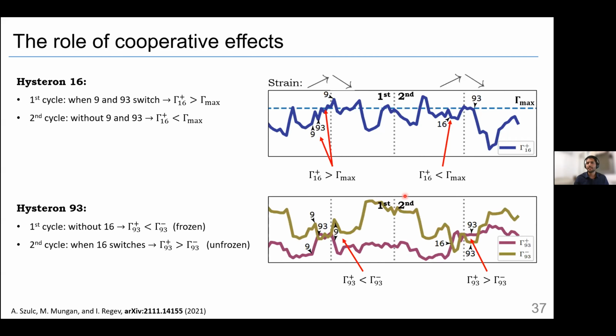Hysteron 93 is a little bit different. This is what we call the frozen state. You can see here in this segment, gamma minus is above gamma plus, so it cannot switch, it's frozen in this segment. But when you get to the second cycle, you see that 16, the effect that it has on gamma plus and gamma minus of 93, pushes gamma plus a little bit up and gamma minus a little bit down, so it gives it a small window to switch. So 93 switches because of 16.